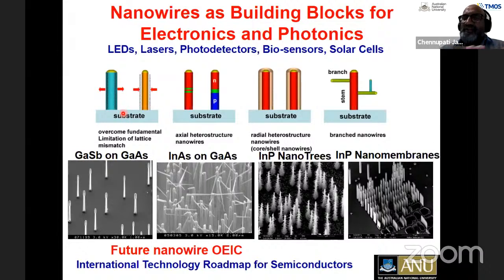Whenever you're dealing with two-dimensional materials, you always have to worry about the lattice constant of the layer you're depositing and the lattice constant of the substrate. Because of their nanoscale and three-dimensional architecture, in principle, you should be able to grow nanowires of any material on any substrate without the constraints of lattice mismatch. If that is the case, then in principle, we should be able to integrate III-V semiconductor optoelectronics technology with silicon microelectronics technology, which people have been working on for a long time. Defects have always limited this, and now we and other groups are working on trying to integrate III-V nanowires on silicon.